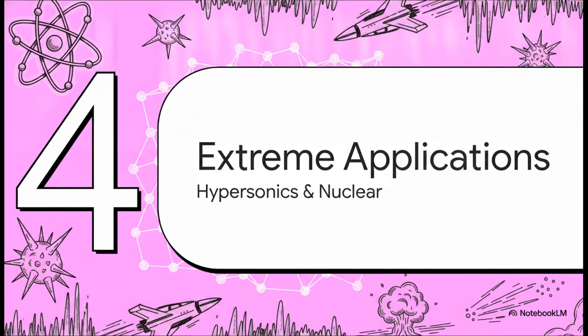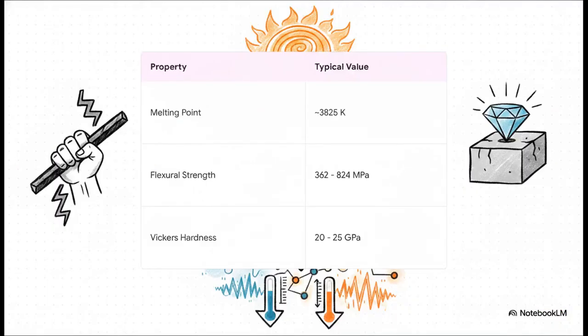Section 4. Hypersonics and nuclear power. When you get all this right, the resulting property profile of these optimized ZrC components is just staggering. We're looking at extreme Vickers hardness, up to 25 gigapascals, and flexural strength that can top 800 megapascals. But the real standout property here is thermal conductivity. Unlike almost all other ceramics, which normally become better insulators as they get hotter, ZrC has this bizarre, almost metal-like thermal conductivity that actually increases as the temperature rises. This is all thanks to how its electrons behave at high energy states.